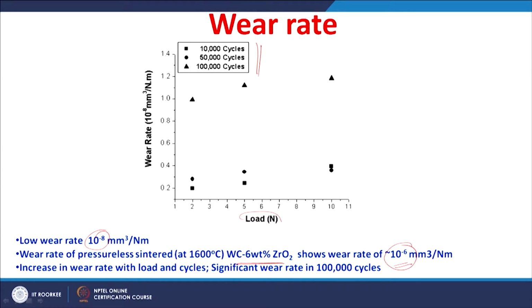Now, at a lower load, the wear rate was less for the test done for a small number of cycles, that is 10,000 cycles. For the test done at 10,000 cycles, even if you change the load, there is not much difference. It changes from around 0.2 to around 0.4 × 10 power minus 8 mm³ per Newton meter. Now, if you see the 50,000 cycle result, again at lower load the wear rate was less and it increases and is then almost the same at 10 Newton load. So, again there is a small increase with the load, but after 5 Newton there is not much difference.